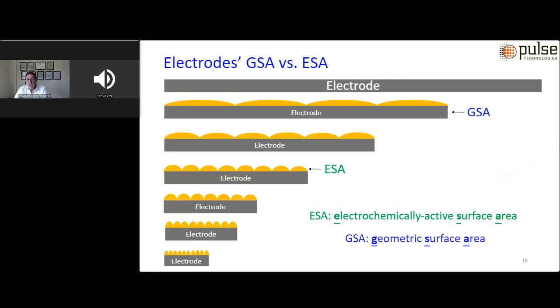Essentially, larger electrodes, as I said, have greater geometric surface area and therefore can inject more charge before they exceed the electrochemically safe limits in the body. However, their large size limits the spatial selectivity and resolution of the device. As I said, in order to increase the charge injection capacity for delivering a higher resolution signal and also improving performance, we can increase the geometric surface area by increasing the number of electrodes.